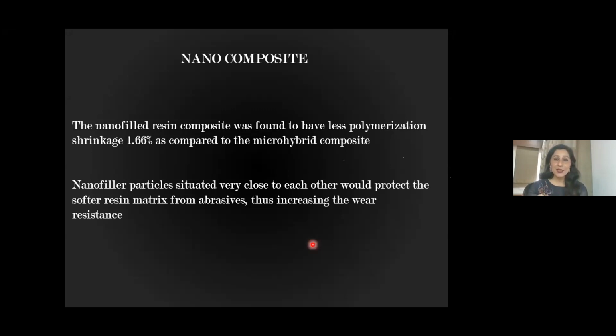And these nanofillers are situated very close to each other to protect the softer resin matrix from abrasives, thus increasing the wear resistance. So whenever you need any composite that has to be wear resistant, also because I told you not to use for bruxers, but if you cannot give metal restorations, or if you cannot give indirect restorations for any cause, the patient is not financially strong, you want to give a low budget restoration, then remember to give nano in such cases. And also remember, because they have low polymerization shrinkage, the chances of marginal staining and micro leakage will be reduced.